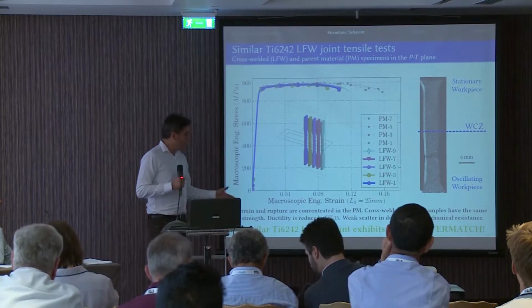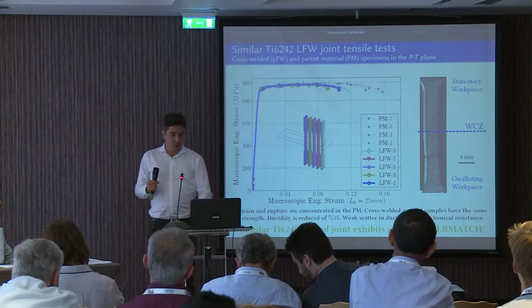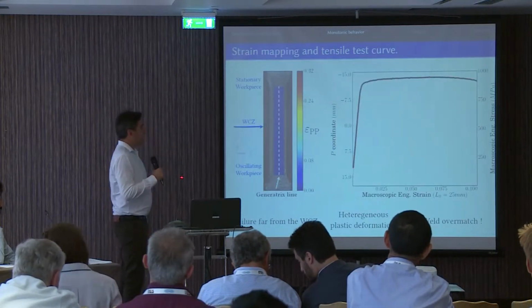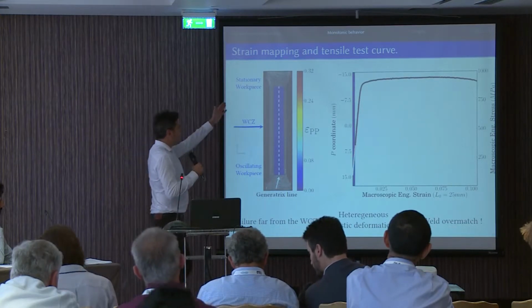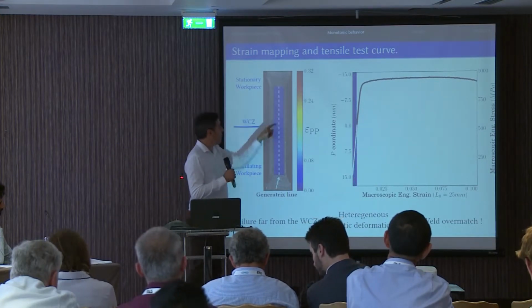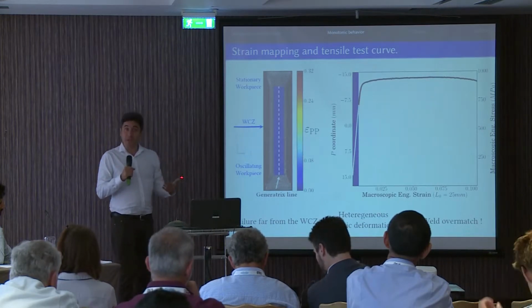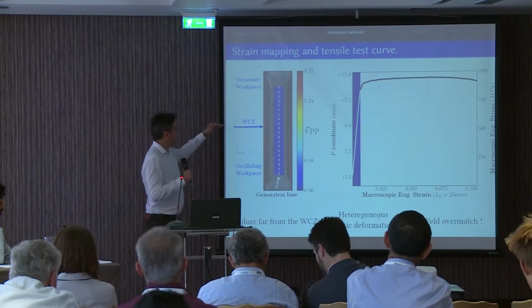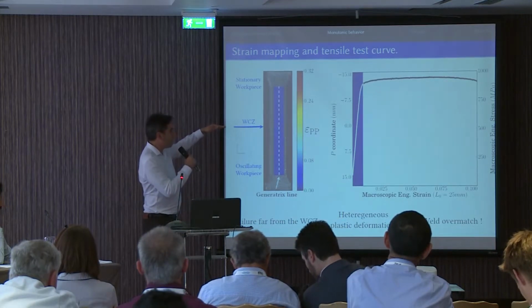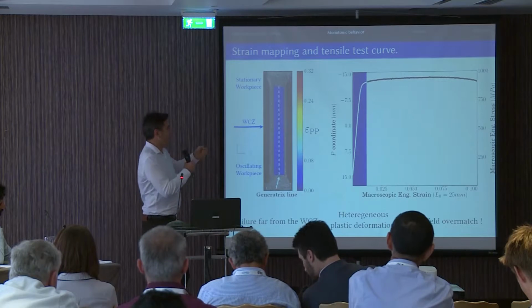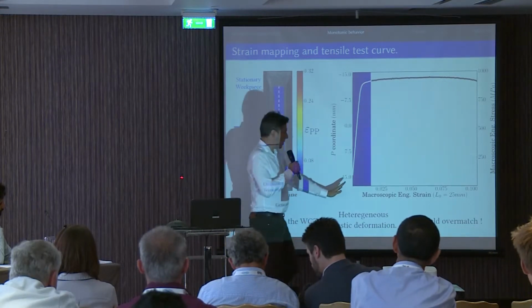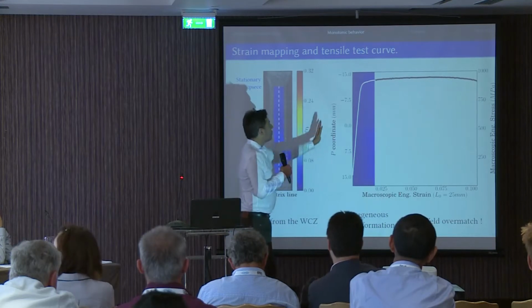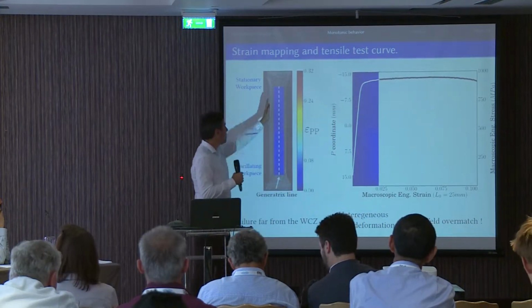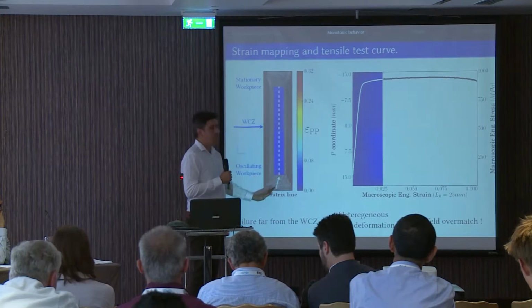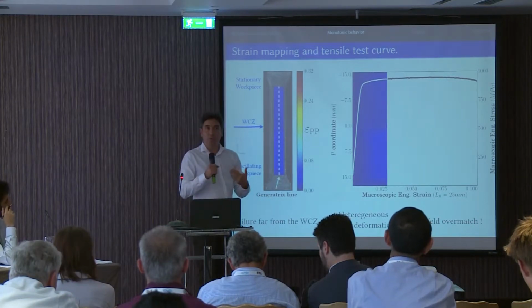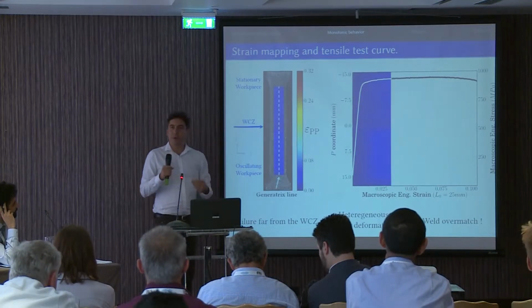Similar Ti6242 Linear Friction Welds exhibit a weld overmatch. Now we are going to study the local behavior. On the right we have a picture of the specimen with the blue rectangle, which shows us the strain field on the surface of the specimen. We have the weld center zone here in the middle. As we pull, for every level of the macroscopic engineering strain, we map in vertical lines the cumulative strain field along this generatrix line. So we are going to plot a so-called spatial temporal graph.